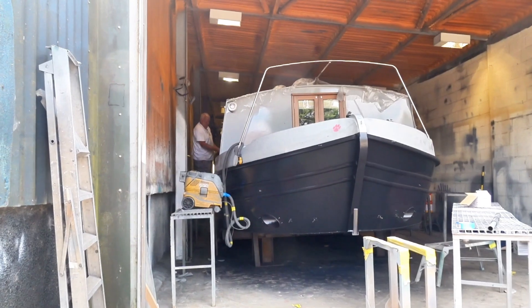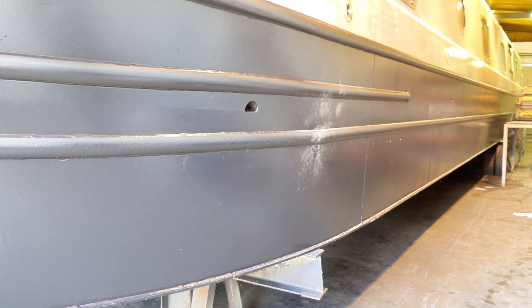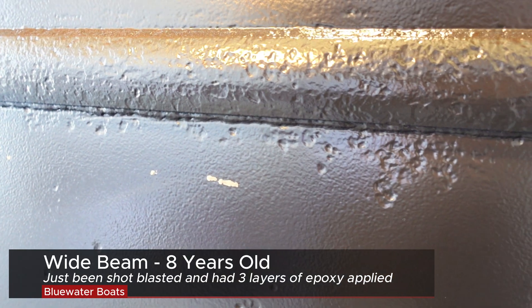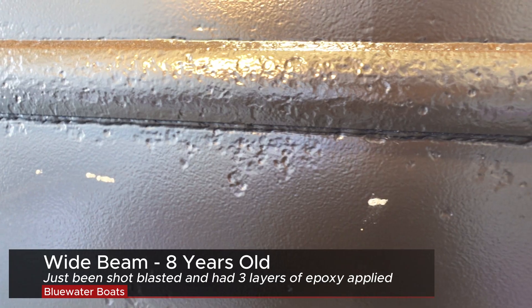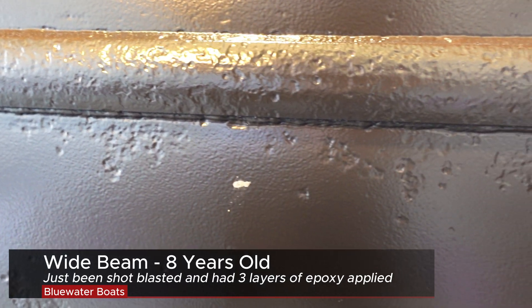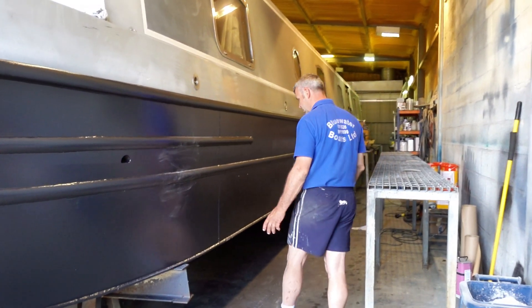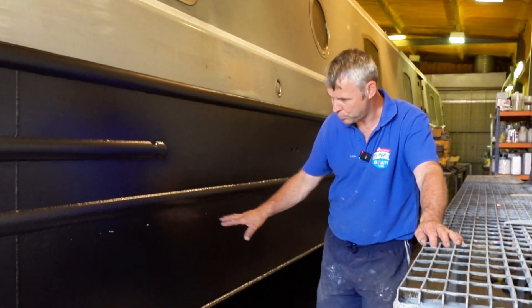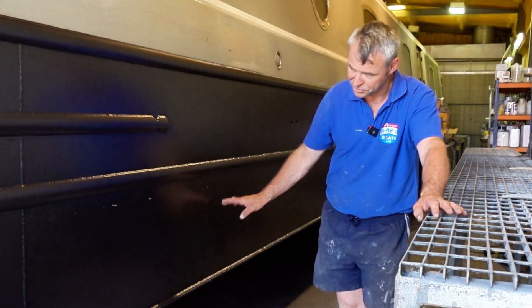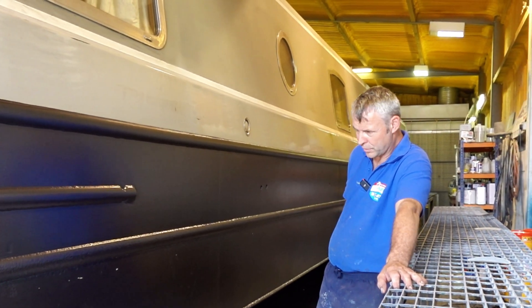One customer has been very lucky — timing's perfect. We've blasted it off and it's exposed quite a lot of pitting. The majority is probably just around about the two mil mark on six mil steel — not the end of the world. It's quite different actually, because it's quite well spread out. Some bits are quite good and some bits, up to about two mil of pitting.